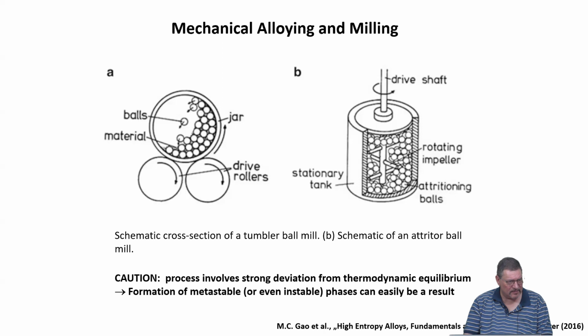Whenever one does these experiments, one has to be aware of restrictions. This is typically a process that occurs far from equilibrium, right? Because you transfer a lot of kinetic energy from the balls or from the mill itself to the powders, which means that defect densities are exceedingly high. Local temperatures could become very high with associated very high cooling rates. So the whole material is in a non-equilibrium state, very far away from equilibrium. And so you could get metastable phase formation, amorphization, and so on occurring.